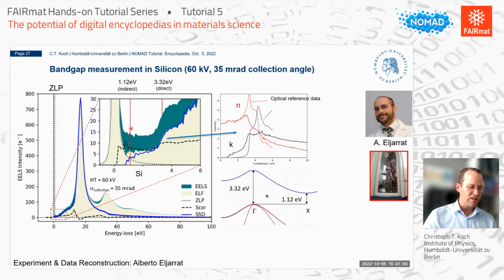You would be able to extract that from the raw data, which is this green curve here, but you have to do some processing of this data to remove relativistic effects and so on. I don't want to bore you with this, but you can then compare it. And that is what I mean by normalizing data. You want to bring the data into a format that it can be compared with other data, in this case optical spectroscopy. These dashed curves are optical spectroscopy data, and here is the dielectric function extracted from the EELS experiment.